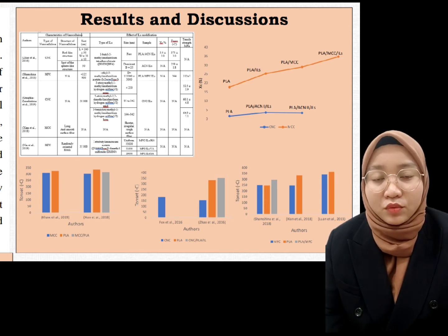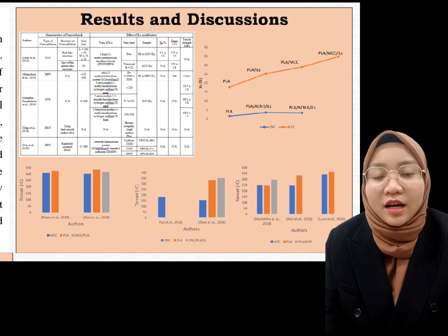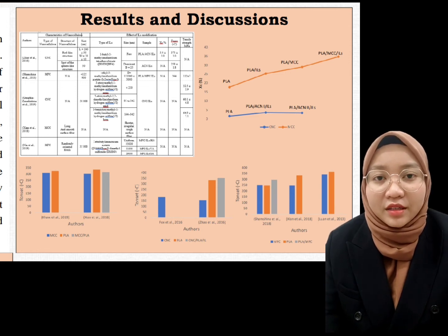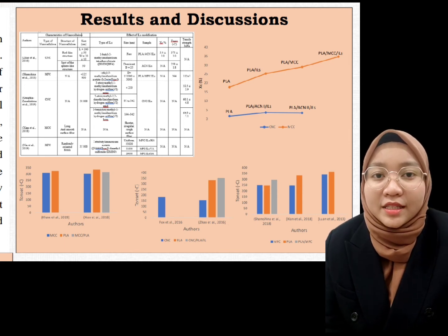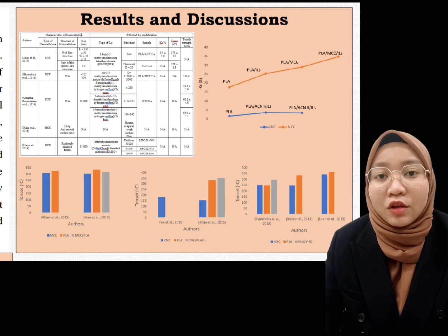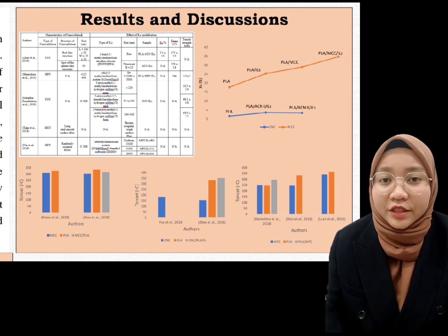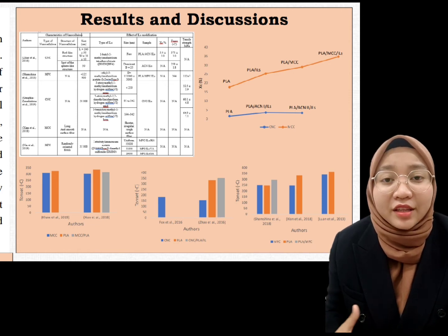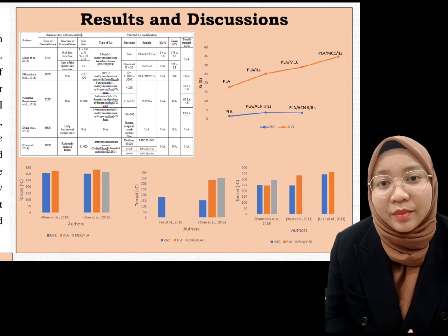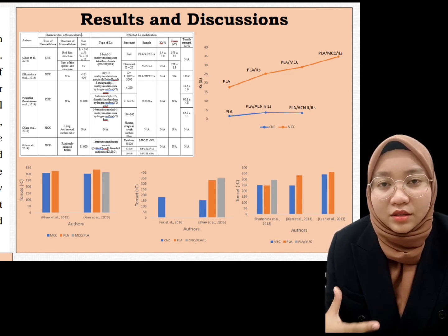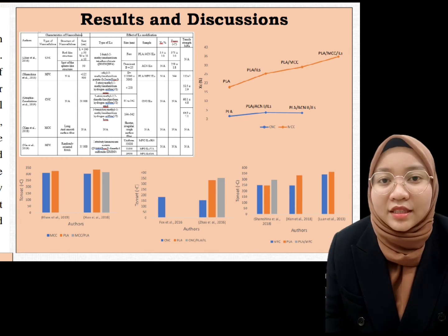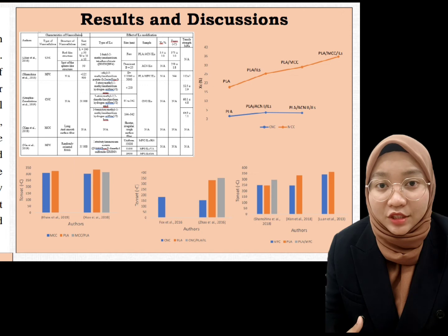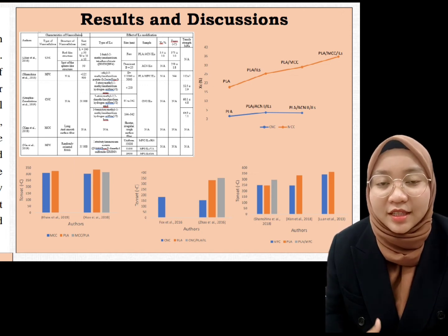Higher crystallinity was associated with lower temperature of crystallinity, but the higher temperature of melting. Crystallinity is also a vital parameter in observations because to achieve ordered crystalline form, MCC has greater than CNC. The mechanical properties also improve as the degree of crystallinity increases proportionally to the chain length. The size and the form of the plastic molecular chain influence its crystallinity percent.